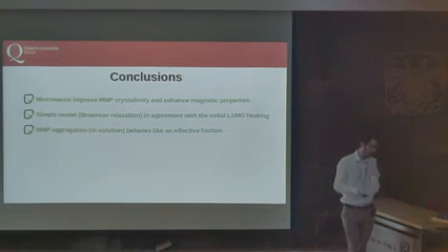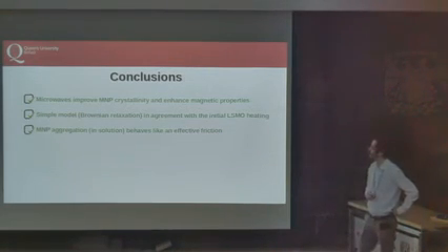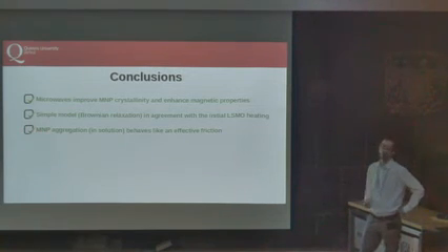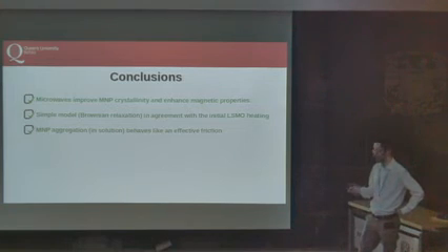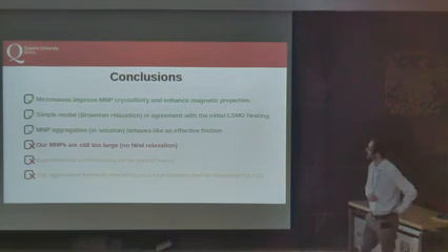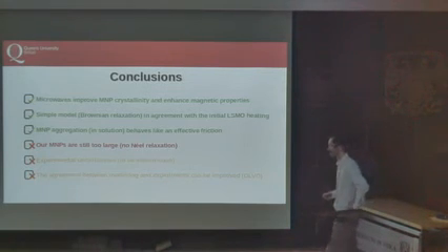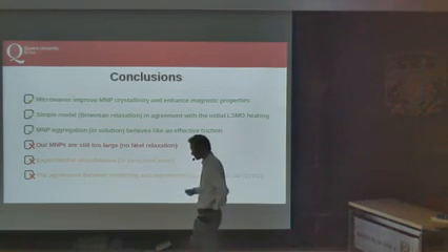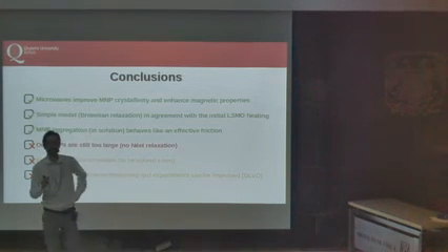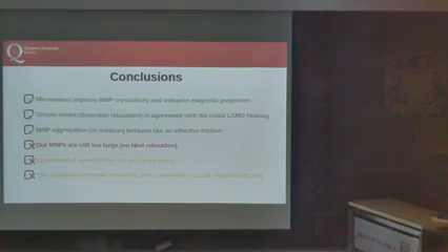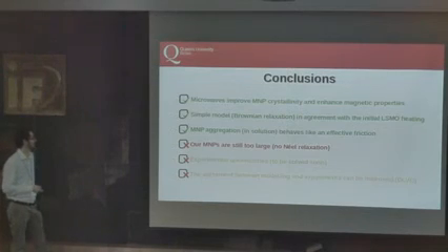And in fact, from molecular dynamics or spin dynamics calculations, we see that the aggregation of magnetic nanoparticles can be described to a certain extent as an effective friction, effective viscosity. Those are the good points. The bad point is that our nanoparticles are still too large. We are happy that they have very good crystallinity, but we still want to decrease the size so that we can also test the Néel relaxation. Our code can deal with the Néel relaxation, but the particles are still too large.